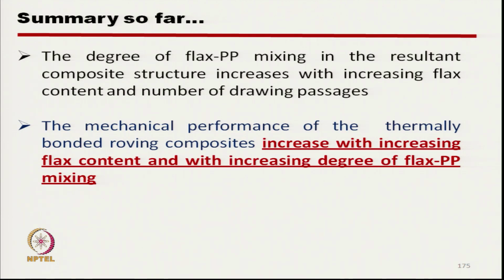So, the summary which we can conclude here: the degree of flax and polypropylene mixing in the resultant composite structure increases with increasing flax content and number of drawing passages, and also the mechanical properties of the composite made of thermally bonded roving increase with the increase in flax content, that is reinforcing fiber content, and with the increase in the degree of mixing, that is number of passages.